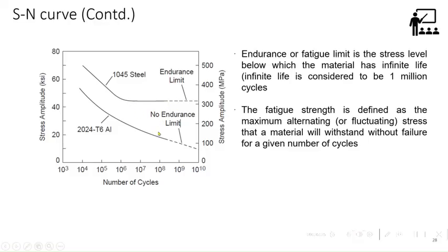So any structure designed from the ferrous material, if you design it to ensure the operating stress is below the endurance limit of the material, you will have infinite life. That is how ground vehicles are able to run overloaded. Whether the bus vehicle, you see it's not only overcrowded, people will be sitting on the top, and nothing happens because weight is not a criterion in the ground vehicle, and they are designed in such a way that the stresses come below the endurance limit, so it will have infinite life. But in the case of aluminum alloy, unfortunately there is no such knee point where you can design. Even if you design below that, still damage keeps on accumulating.